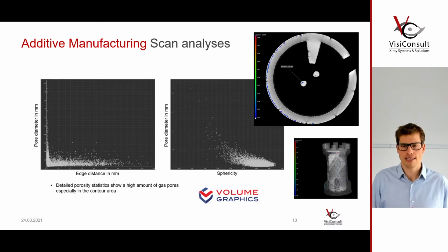And this creates a situation where, first of all, you have a temperature gradient before they're already sintered outside. And you have different laser intensities and temperature inputs between outside and inside. And this is creating an area between the hull and the inside, which is prone to have defects or porosity.